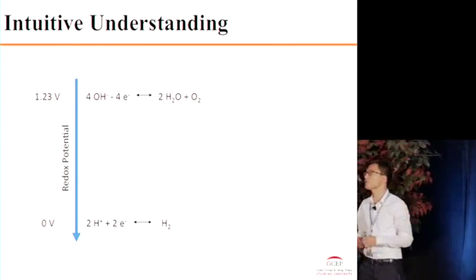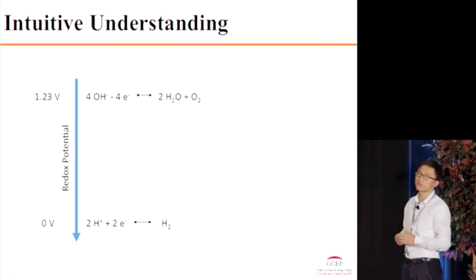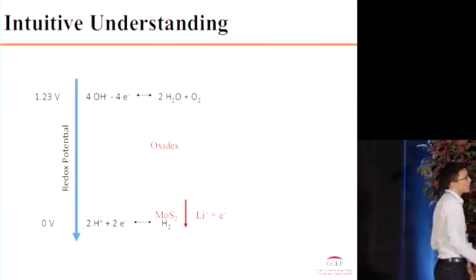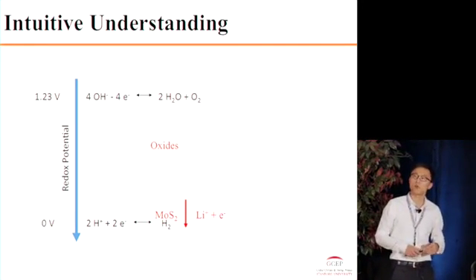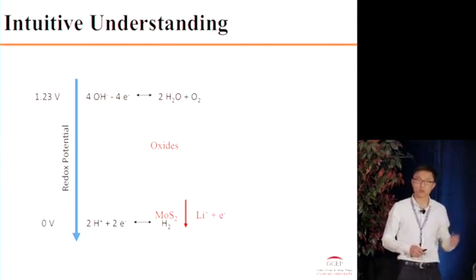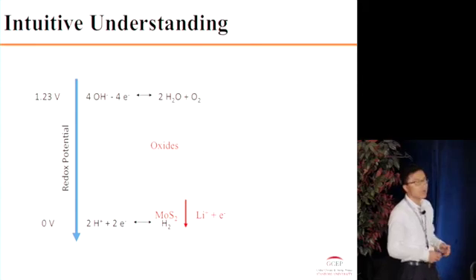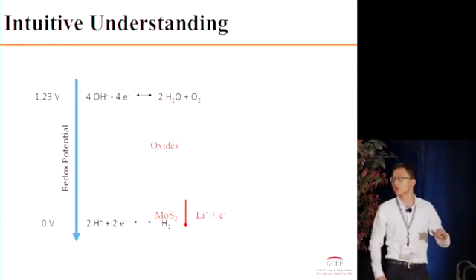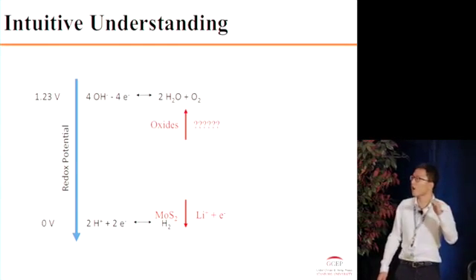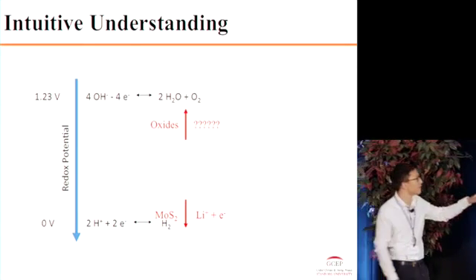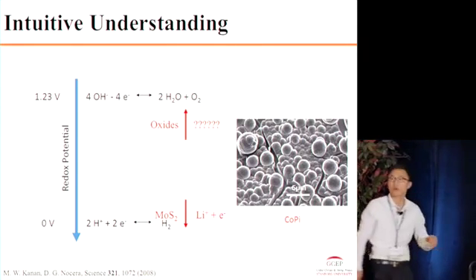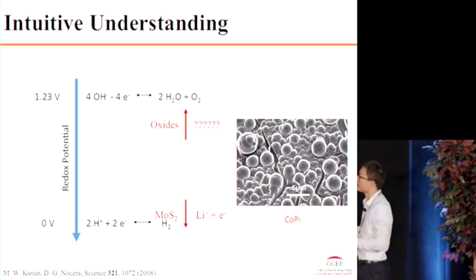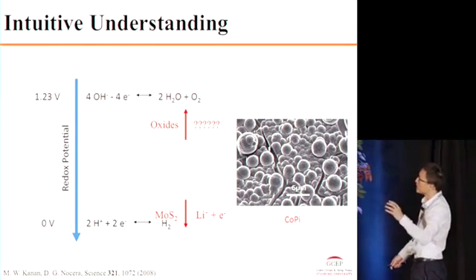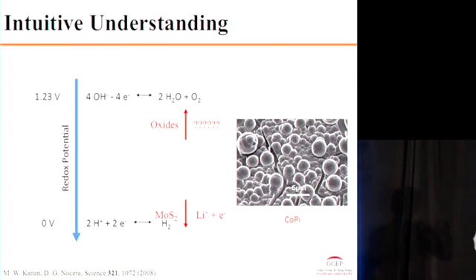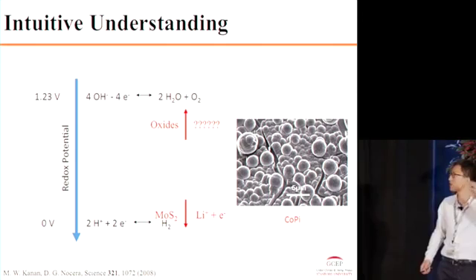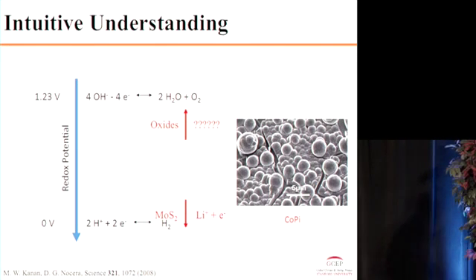And this successful demonstration of electrochemical tuning to improve the catalytic activity strongly drove us to see if we can do similar work on the other half reaction of water splitting, that is the oxygen evolution reaction. But instead of bringing down the chemical potential of your catalyst, we're trying to bring it up, because the oxygen evolution reaction is at a much higher voltage than the hydrogen evolution. And this correlates very well with Professor Kanan's previous work when he was a postdoc: if you have a higher oxidation state of the transition metal, such as cobalt, you might get very good OER catalytic activity.